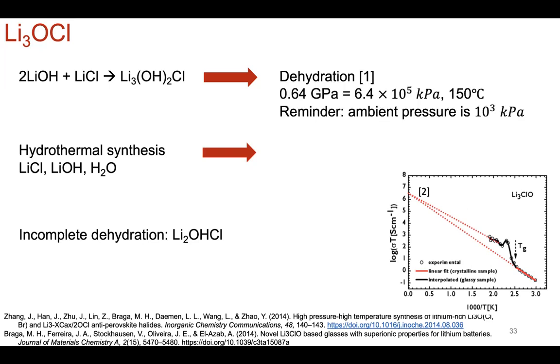The only issue is, of course, dehydration. So these compounds, if you notice, when you start off with lithium hydroxide, you form an intermediate here. That's not the final compound. It's Li3OHCl. So now you're going to have to dehydrate and remove the H2O. So dehydration typically can occur one of many ways, right? We stick it in a vacuum chamber. Sometimes that does a good enough job if the compound is moisture resilient, so that's seen in lithium indium chloride. You can really have this compound be in a humid environment, then you put it in a dry room, and all of a sudden ion conductivity shoots straight up. So compounds like that are easier to work with.